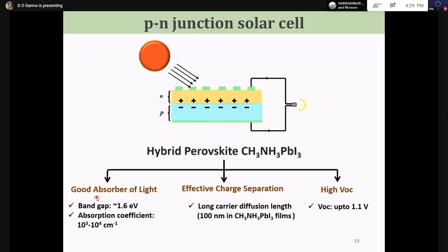What are the properties with respect to these? It is a good absorber of light, I said. The band gap of this material is in the order of 1.5, 1.6 electron volt. The ideal band gap for a material to absorb sunlight most effectively in the normal configuration is a little less than 1.4 electron volt. So it's very close to the ideal band gap.